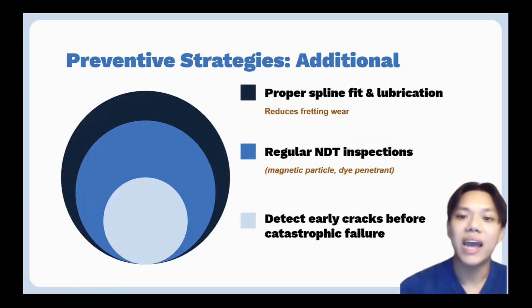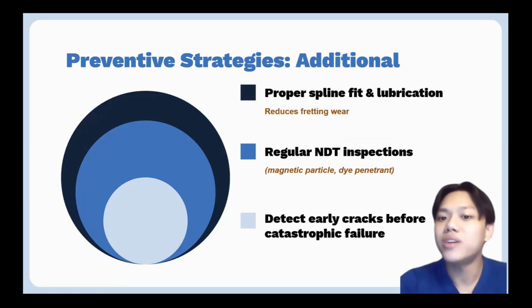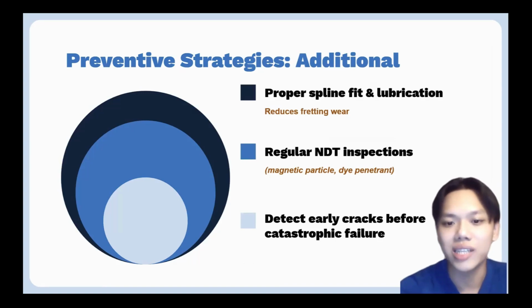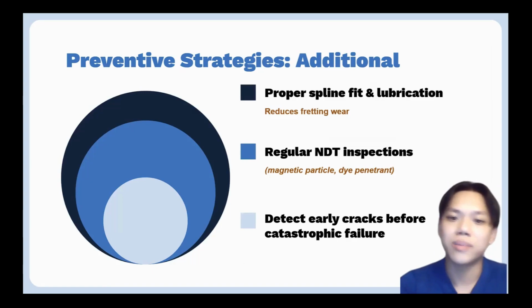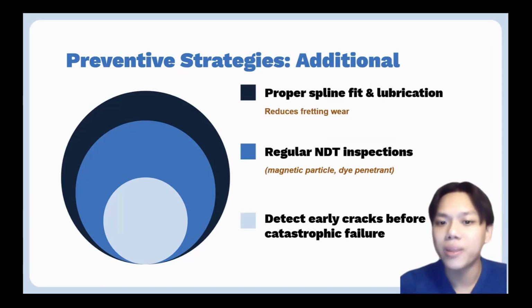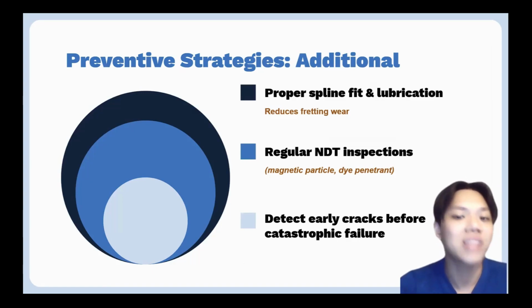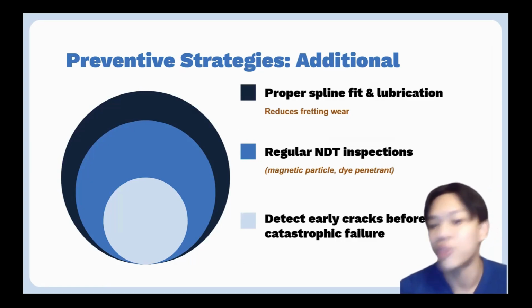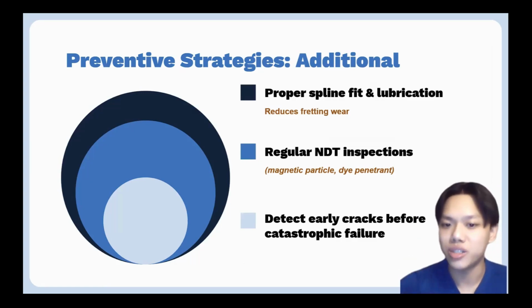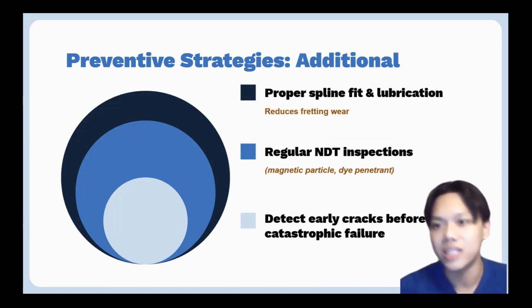Lastly, additional measures can be taken to further reduce the risk of premature failure. Ensuring that the splines are properly fitted and well lubricated minimizes fretting wear, which can otherwise accelerate crack initiation. In addition, applying non-destructive testing methods such as magnetic particle inspection or dye penetrant testing allows early detection of cracks before they reach a critical stage. These preventive measures add an extra safety margin to help ensure reliability during racing conditions.